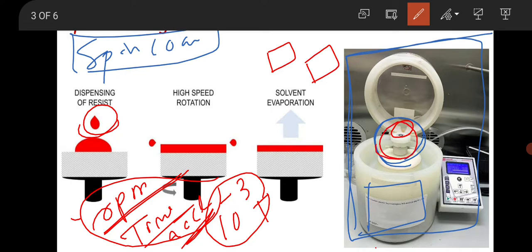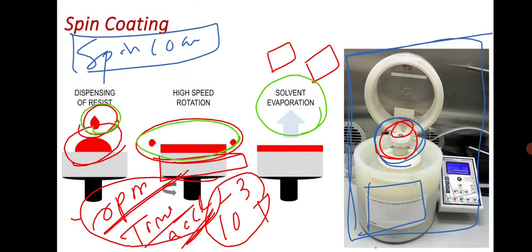After setting these parameters you start the program so that the rotor begins rotating in a clockwise direction. When rotation starts, your liquid will spread over the substrate. This is the substrate and this is your film being fabricated. After the deposition the liquid is spread over the substrate and you get a film like this. After that you take this film out and provide a heat treatment to the material in order to grow the crystalline phase and to evaporate the organic solvent from the precursor. Your material in pure phase will then be formed on the substrate. This is the basic spin coating technique for fabricating a thin film in a simple and low cost way.